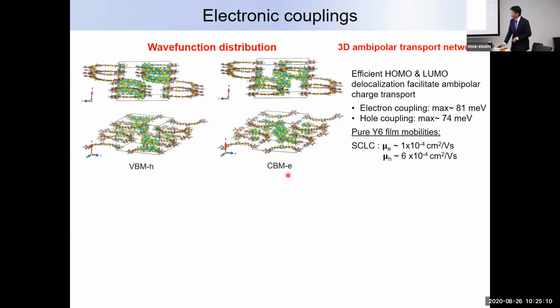And the one showing here is for the LUMO delocalization. So you can see the LUMO is more delocalized in the vertical direction, because those acceptor molecules are stacking on each other. So this stacking creates a very nice electron transporting channel for this material. So we modeled this electronic coupling, where for both electron and hole coupling, they are quite similar and also quite large. That means they can facilitate a decent charge transport.